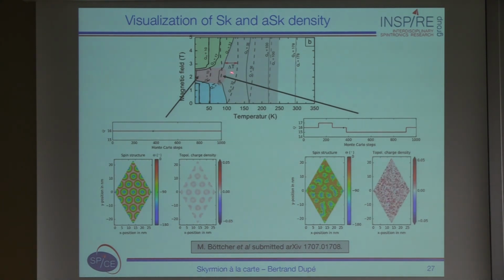However, if you go into this region here, at the border between the gray shaded area and the red area, you see that you have a lot of motion of your spin texture, and you cannot correlate the topological charge density to the spin texture anymore. You can even create more skyrmions than in a skyrmion lattice, so you can pass to Q equals 17, and you can also decrease the number of skyrmions. It looks almost like a fluid, and if you look carefully, you will see that although here you should have only skyrmions, you have some blue dots appearing and disappearing all the time. It shows that here it's like a vaporization of topological charge, or like a topological charge liquid.